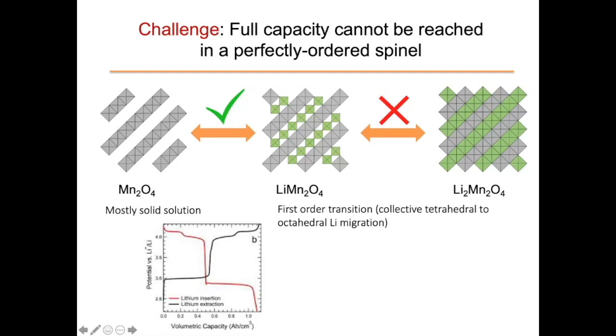The origin of this first order transition is the fact that in a spinel, you have the manganese octahedral and the lithium tetrahedral. And when you try to add an ion to that, say by intercalation, you necessarily need to phase share with some other ion. And cations don't like to phase share. So what the system does instead is push all the ions octahedral. This is an important thing to know. If you want to make a structure in an FCC anion framework that has both tetrahedral and octahedral ions, then spinel is the best you can do. It is the highest amount of cations you can put in a structure. As soon as you want to put in more, you have to phase share ions.